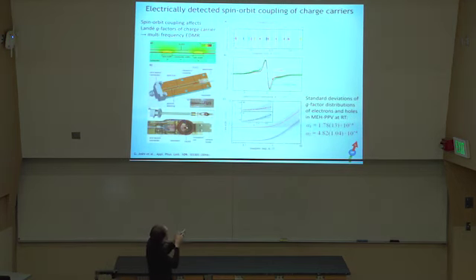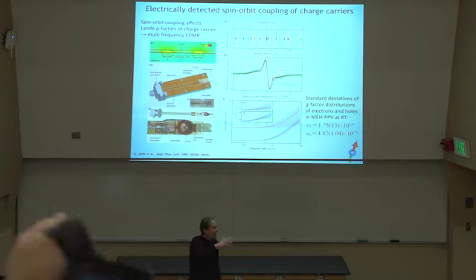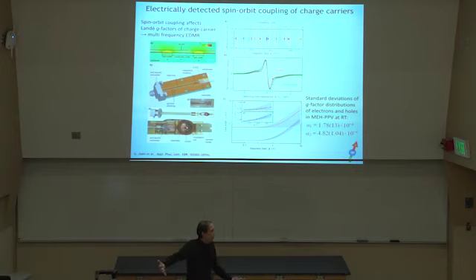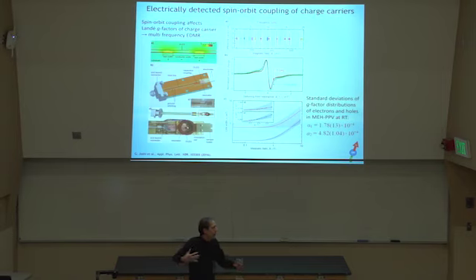And this is data for MEH-PPV that I didn't show earlier. The different colors here represent different resonators, different lambda over 4, and their higher harmonics. And by doing this, we can cover a whole range of frequencies. And then, of course, for high magnetic fields and frequencies, essentially past 20 gigahertz, then you have to do it optically. So then you have a quasi-optical setup, basically a terahertz setup, and you use corrugated waveguides to couple your millimeter waves into your samples, and then you need millimeter wave optics.